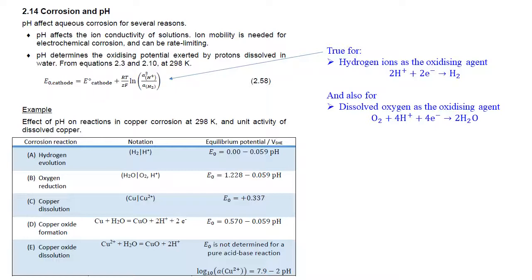A low pH or a high hydrogen ion concentration in an acid means that there's a lot of positive hydrogen ions hanging around in solution, and it should be no surprise that these environments are able to be more strongly oxidizing, because to be oxidizing simply means to be able to absorb electrons, and those protons are able to do that. So low pH, intrinsically, other things being equal, means that some of these oxidizing agents are slightly more oxidizing.